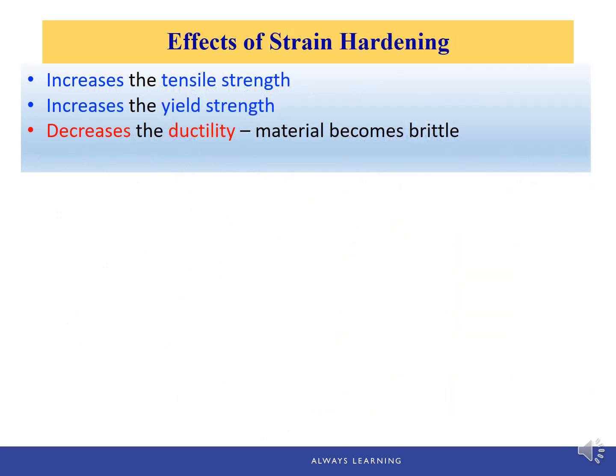We know that after strain hardening or cold working, the tensile strength and yield strength of the material will increase, while the ductility of the material will decrease. In addition, at microscopic level, the grain shapes will change as well. The grains are elongated. For example, the aluminum beverage cans are formed by deep drawing, which is a form of cold working technique.